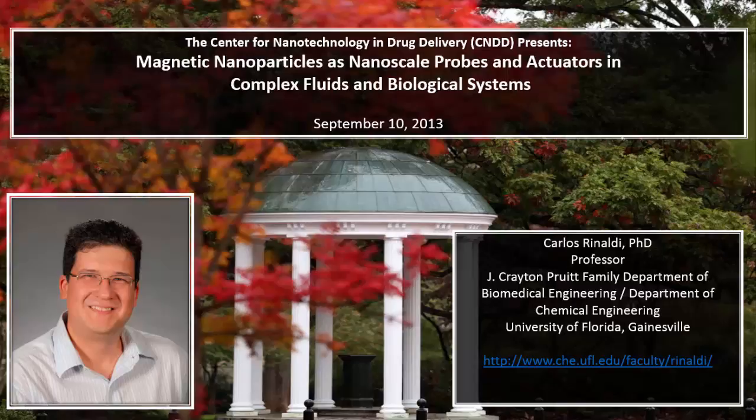And if you look at the Debye model, what that says is that when you hit the transition, this term here is going to increase very quickly with temperature, which means that this parameter here is going to decrease very quickly with temperature. On the other hand, when you look at the out-of-phase component, this term is going to increase very quickly with temperature. So these measurements are consistent with the idea that the hydrodynamic drag on the particle is increasing dramatically as we cross this temperature.